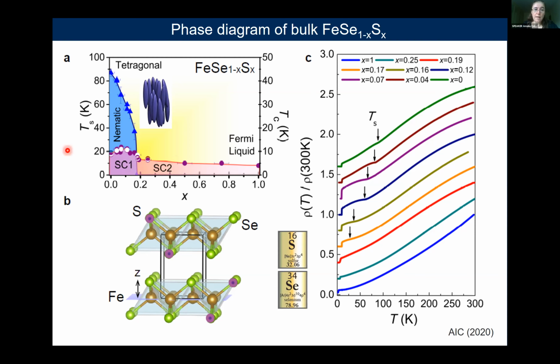Furthermore, if we look at the phase diagram here on the left, we have the position of the structure transition and superconductivity. All these are obtained from measuring resistivity versus temperature. And here we have the kink at about 90 kelvin for iron selenium, and as we add sulfur, this transition is further suppressed. So in a crystallographic way, the sulfur and selenium occupy positions outside the iron plane, which determines all the electronic properties. And often how far away this ion is is very influential on the electronic structure.